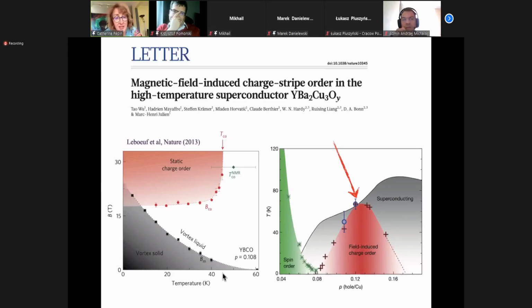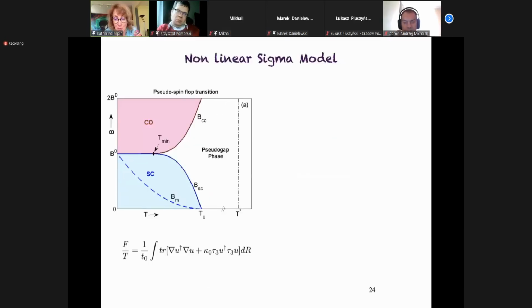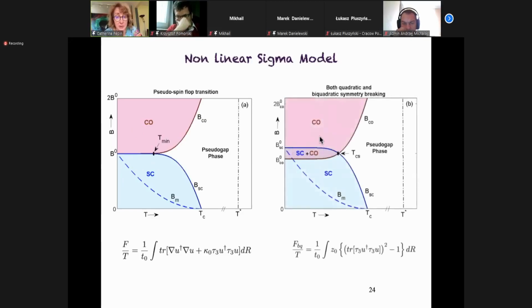So my belief, it's still a belief, it's not an epiphenomenon, and we checked this phase diagram with pseudo-spin flop transition within the nonlinear sigma model. The nonlinear sigma model has a constraint between the two orders here. So the constraint is naturally giving you this flatness. If you instead use a Ginzburg-Landau to model the data, you need to fine tune like crazy to get the flat region. Moreover, you will never be able to get with the Ginzburg-Landau the coexistence that we get naturally within the nonlinear sigma model if we break a little bit the SU2 symmetry.